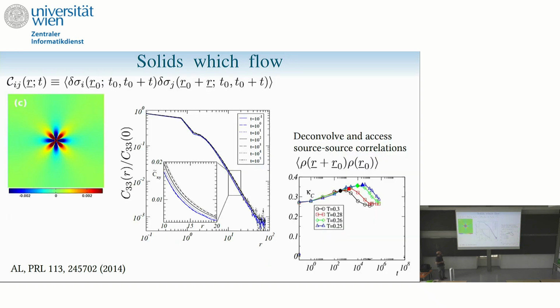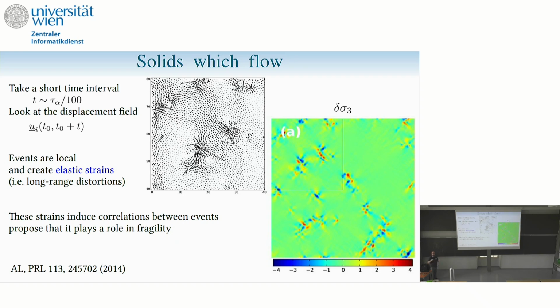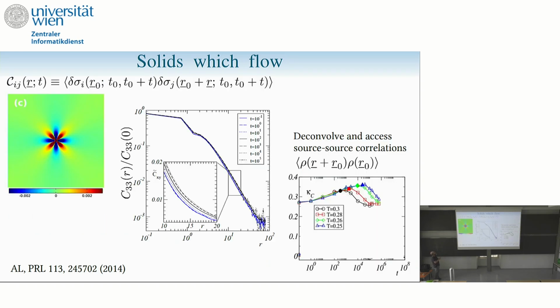And in fact, if you look at the shear strain field, before I was looking at strain, it turns out that strain is a very complicated observable to define, because what happens when two particles swap their position? Strain is not a very nice observable. For somebody doing numerical simulation, stress is much nicer because it's very well defined. So you can take the stress in one configuration, look at the stress in the next configuration, take the difference, and you have a stress difference field. And when you look at the autocorrelation of the shear stress in a liquid, you see a beautiful Eshelby pattern. You can take a cut through the lobes and you see the 1/r² law. So you really have elasticity in the liquid.